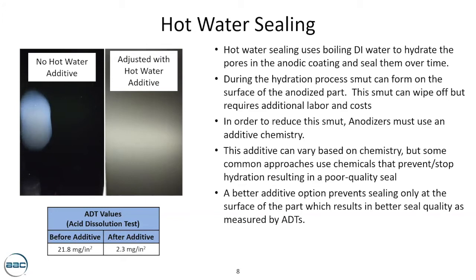There is one panel which is dyed black that has no hot water additive, and another part of the panel that's dyed gray, which does have a hot water additive. And you can see there's a pretty significant white water stain on the part on the left. With boiling DI baths, after a part has been immersed in there for more than 4 to 5 minutes, you start getting hydration throughout the anodic pore all the way up to the surface. And the surface hydration is what shows the majority of the smut.